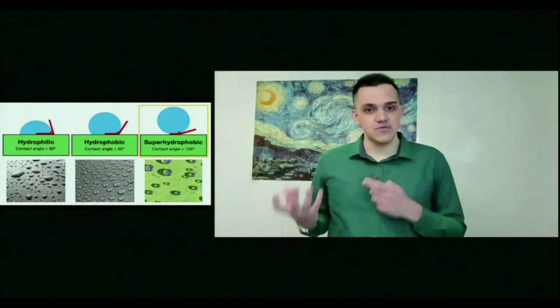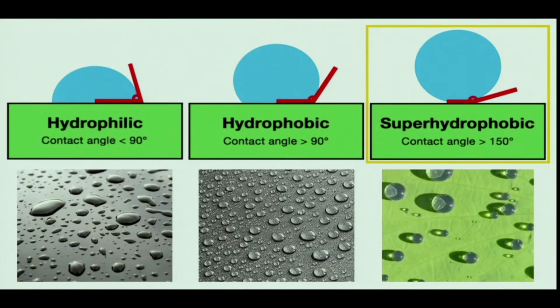And to be considered super hydrophobic, the surface needs to satisfy two conditions. First, it needs to present a contact angle equal or higher than 150 degrees. And second, the water droplets must easily roll off the surface with the lowest contact area between the water and the surface. And that brings us to the second variable, the contact area. And as I said before, the main factor to create super hydrophobic surfaces is the combination of micro and nanometric structures, which is also called hierarchical structures.